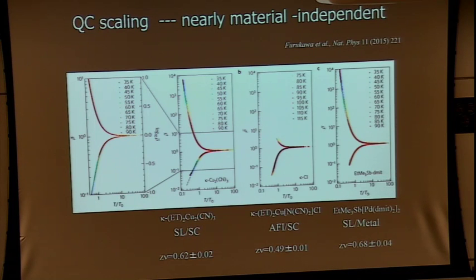And this behavior is not specific to the spin liquid materials. This high temperature behavior is commonly seen in other Mott transition systems. We examined the behaviors for different materials having different ground states. These materials are antiferromagnetic insulators and superconductors. And these materials show, in the insulating phase, a spin liquid and, in the metal, no superconductivity. So a different set of ground states appears in different materials. However, the scaling is nearly common, nearly the same.